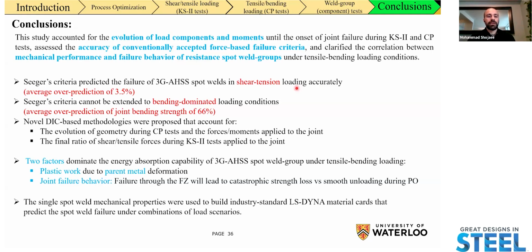But Seeger's criteria cannot be extended to bending dominated loading conditions, where we had a huge amount of over prediction in terms of the bending strength, up to 66%. In our study, we also developed novel DIC-based methodologies that can be used to account for the evolution of the geometry throughout different mechanical tests and give us the instantaneous values of forces and moments that are being applied to the spot welds.